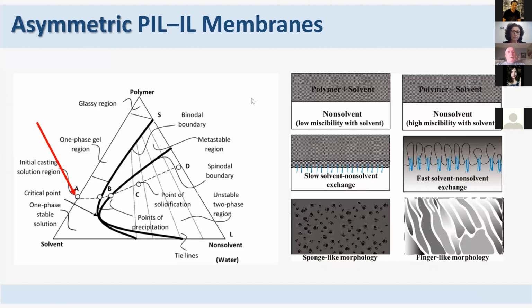So what we are aiming to do is, we have the initial casting solution here, and we have this polymer, solvent, non-solvent equilibria. This is how we're trying to promote porosity. And we determine the initial casting solution, this critical solution, through viscosity measurements. And then when we put our membrane in the bath, the concentration starts changing and we see it starting to become a little bit jelly, then to precipitate. And as the solvent is being exchanged by the non-solvent, we can see the membrane forming until next morning when we take the membrane out of the coagulation bath.